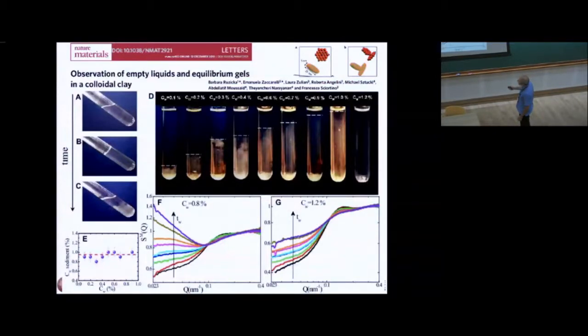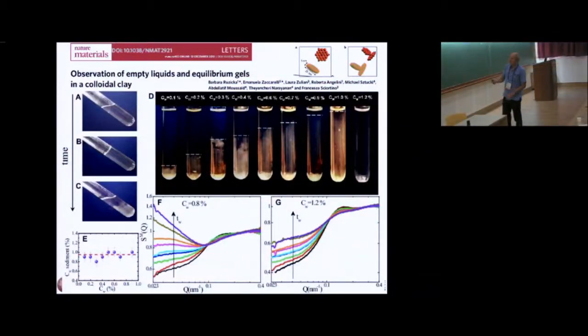Okay, so let's see this system here. If you do the experiment, what you see is that if you prepare these samples and let them wait for months, then they phase separate, at very low concentration, less than 1% in weight. You can rebuild the density of the 2 phases by estimating the meniscus position, and you see that the density is exactly the same, which means that it's a phase separation between 2 phases which have the same properties. The system starts from a fluid, becomes a gel, and then separates in a gel and in a fluid phase.